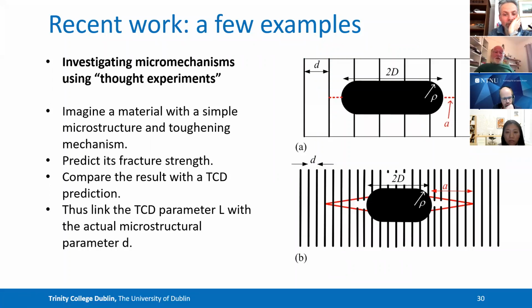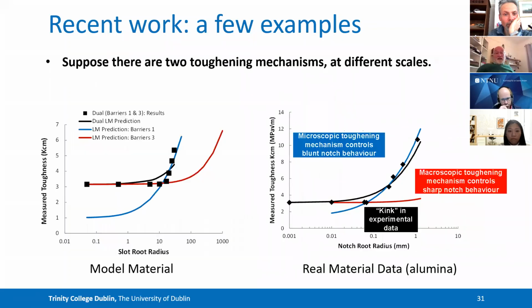I've also done quite a lot more work, published several papers looking at micromechanisms, and I won't go into this, but it basically is a case of imagining different toughening mechanisms, like the effect of a barrier here, or the effect of unbroken ligaments like fibers in a composite material, bridging the crack, modeling those in a simple way, and then seeing how the TCD can predict them. And in one paper published last year in the TAFM journal, I imagined actually two different mechanisms operating at two different scales, because we often find this in materials, that they have maybe grains and also fibers or other mechanisms operating simultaneously.